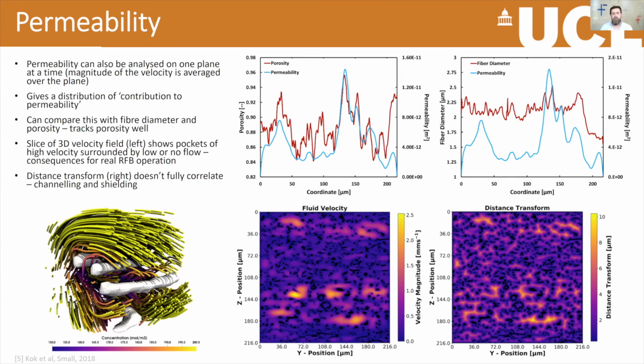So in that way, it wouldn't be a direct relationship, I guess, right? Because you'd have some overall permeability of that material, but you might have a worse performance than that would otherwise suggest, because you've got these heterogeneities in the material, if that makes sense. So all of those things are directly related to the permeability, but then the permeability doesn't necessarily directly marry up with the performance of the battery based on the microstructure. So these things are slightly more complicated than that.